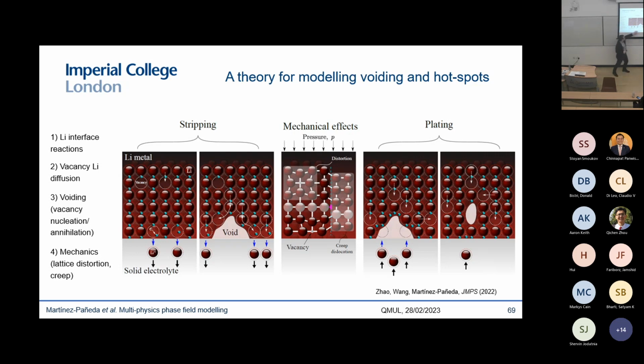And this is nothing but an interface that is evolving. So this is a perfect problem, again, for phase field modeling. So again, multi-physics and phase field, because we have an interface that is evolving, in this case, the voids. And of course, we have quite a lot of mechanics in here. So you have a lot of lattice distortion. And more importantly, the main hypothesis nowadays in the solid-state battery community is that you can suppress those voids by applying a mechanical pressure through creep and viscoplasticity.